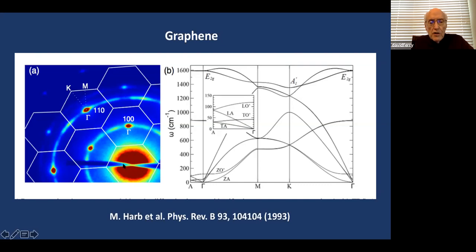And so the bright red is where you're seeing strain in the crystal. And the strain is observed by these phonons right down here, which are blown up here. So the ZO prime here is what's called LO prime up here. LA comes down, TA, and TO prime. What ZO means is that's vibration normal to the graphene plane. So you have these phonons, and this really bright thing says you're exciting phonons in the gamma point. That's this point right here. So these phonons are being driven out of equilibrium. And those are going to be the secondary phonons in decay of big LO modes from up here. They're going to go down to here in some of these. So you can actually measure these and see how far out of equilibrium they are.